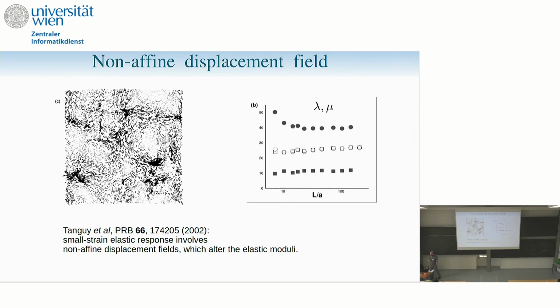So it was noted a long time ago, and I will show you a bit more why, that if you look at the elastic response of a glass, they were not looking at plasticity properly. They were taking a sample of a relaxed glass, looking at the strain response and measuring elastic moduli.